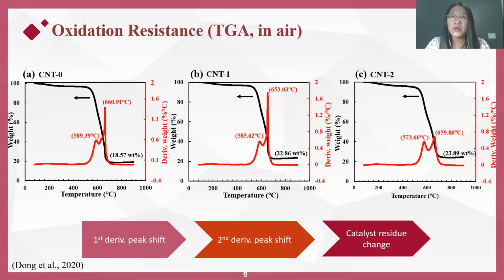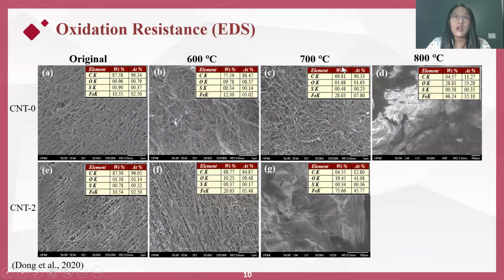We have also noticed a surprisingly increasing trend of catalyst residue from 18% all the way to 24%. The catalyst residue is the residue weight percentage at 800 Celsius. To better understand this trend, for CNT0 and CNT2 group, we took out samples during the TGA at 600, 700, and 800, and we examined those specimens using SEM and EDS. For the as-synthesized samples, the EDS results indicate a similar catalyst residue starting point at 10.55 and 10.54%, presumably due to the identical synthesis condition, except for the water concentration, of course.